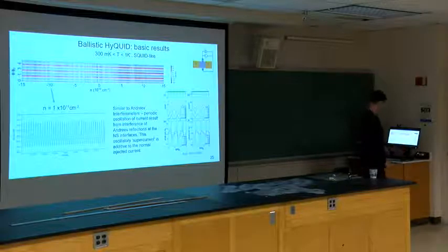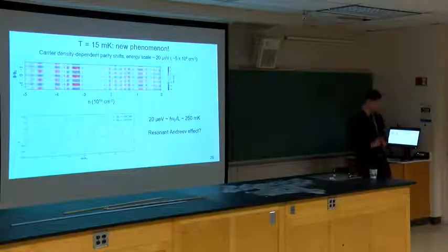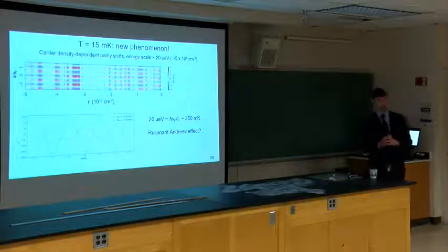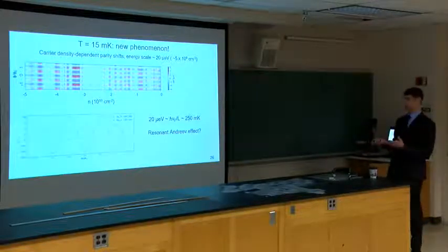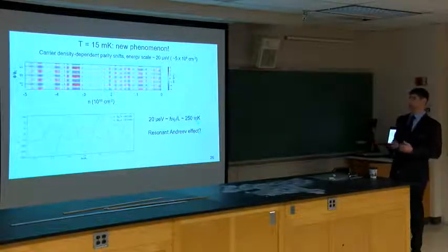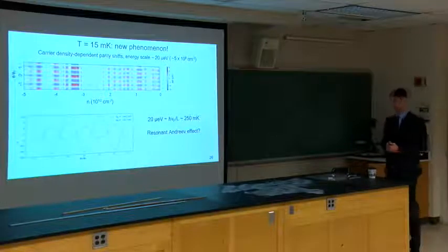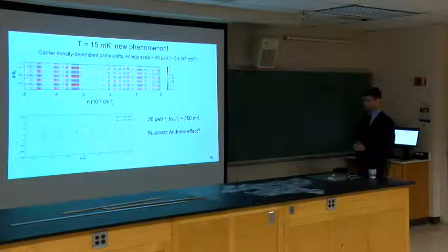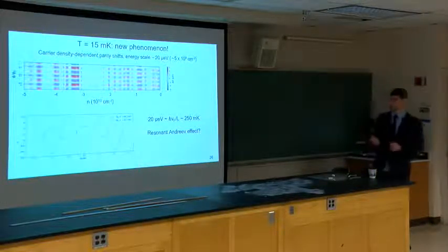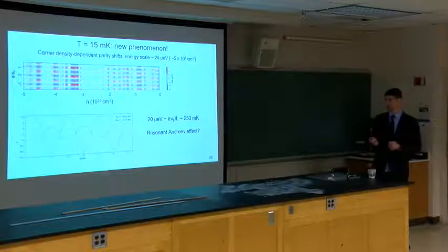So what's interesting here? Well, if we drop the temperature, the Thouless temperature here is something like 250 millikelvin, and it turns out, surprisingly, that when we cross roughly that temperature, we start seeing general weirdness.